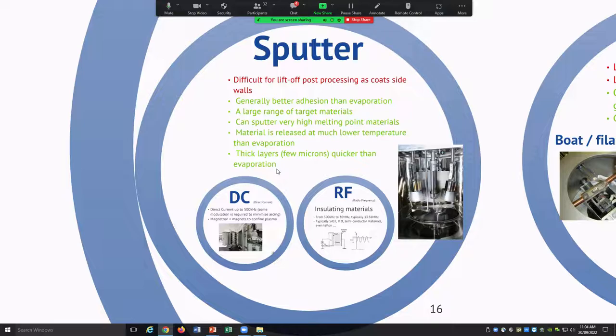It uses a magnet pack to help confine a plasma in front of your target, and then either a DC or an RF applied power supply to create that plasma. What's good about it? It's fairly high energy, so because you're using an electrical discharge to create a plasma, you're accelerating your atoms with that potential, so they have a fairly high arrival energy, which means that you can get dense coatings out of it. Pretty much you can sputter almost anything, any sort of metal, dielectric, ceramic, plastic even, you can sputter it if you really want to. The end result, we'll see what we get, but we can try.